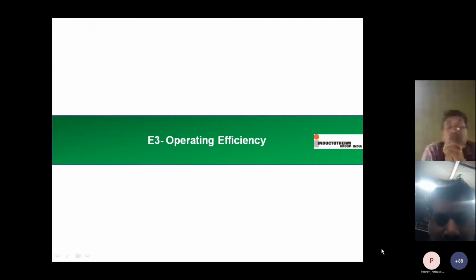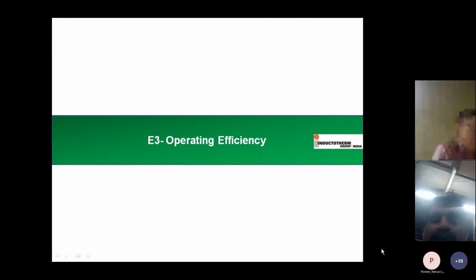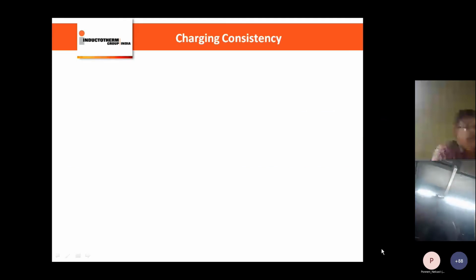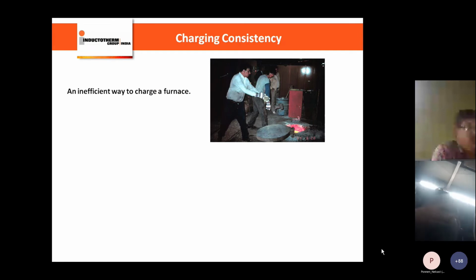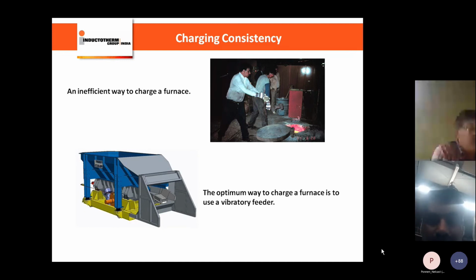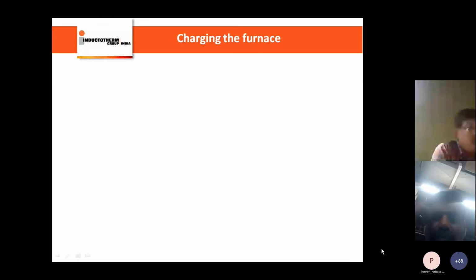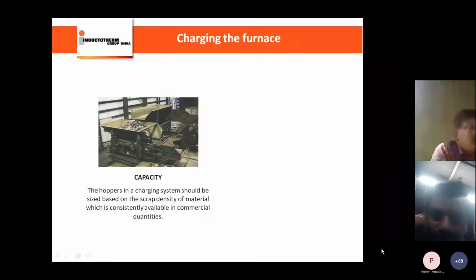Let us touch on the operating efficiency. What are the factors in the E3? Mainly it is the charging consistency. Manual charging is an inefficient way of charging the furnace. The optimum way to charge a furnace is to use a vibratory feeder. Charging consistency is about how fast the charge is fed into the furnace, matching what the furnace demands, or the rate at which power is pumped into the furnace. If you fail to do so, it ends up with higher power consumption and many other problems. Similarly, the hoppers in a charging system should be sized based on the density of the scrap material that is consistently available in commercial quantities.